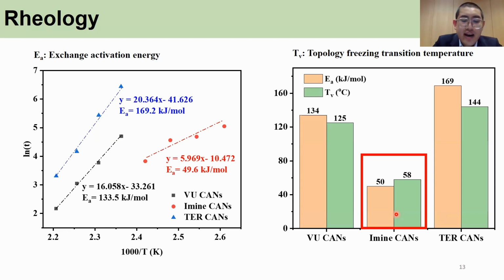Even though the dialdehyde content is only 7% of the total network weight, it still increased the amount of dynamic bonds in the system. And these bonds are temperature sensitive. As a result, the material shows a lower activation energy at TV. On the other hand, the transesterification kinds show the highest activation energy at the TV. This is due to the unique nature of the chemistry.